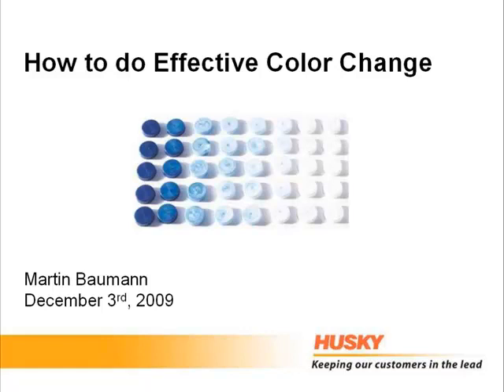There's a very specific question in regards to an 18 cavity mold with a 150 gram part, and the question is, from an opaque point of view, is there any potential problems? And I think in principle I would say no. I don't know which kind of hot runner or what kind of system you use, but typically the colorant itself, no matter if you make it opaque or with a solid color or a different material, usually does not have an impact in regards to part properties. I think what is more important is that you have an overall good process and actually do some testing with a specific resin afterwards. But from a foreseeing problems perspective, I would say no, because oftentimes you have other additives in the parts too, and in a way a colorant is just one of the many additives that you can have.